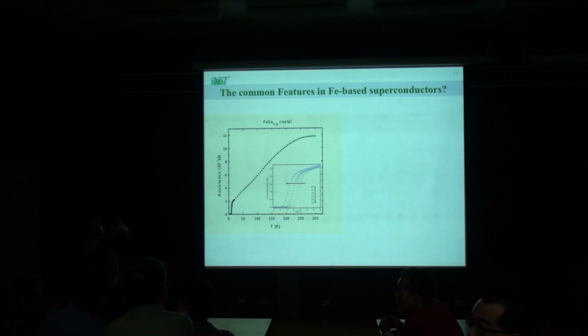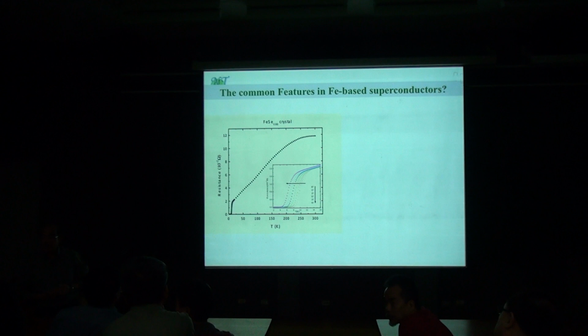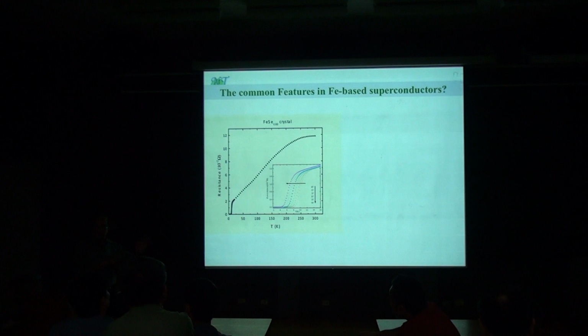So this is the iron-selenide compound. In terms of electronic structure, you don't have to have any moment. It has an antiferromagnetic background. When it's non-superconducting, it has an antiferromagnetic order, similar to the iron compounds. But it's non-superconducting, which means this is with the order of vacancy. That you can calculate, and all that can be calculated. Any other question from students?